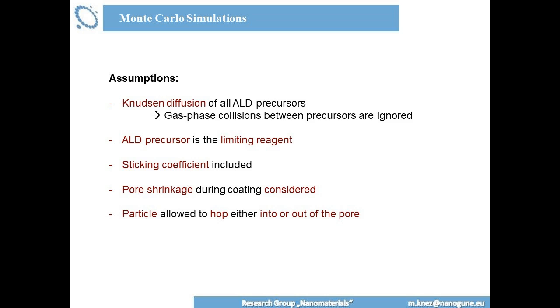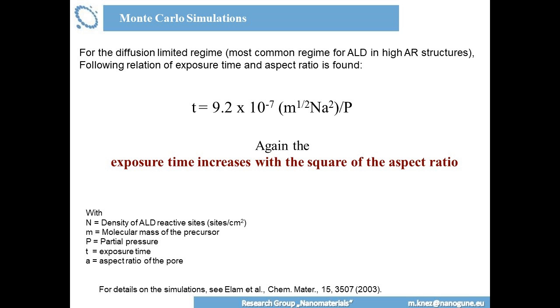So this is also considered in this model, and particles are allowed to hop in and out, so this is also a more, let's say, practical case which is considered, so not only in-diffusion but also out-diffusion. But at the end, all of this is probably going too detailed, but just to give you an idea: the Monte Carlo simulations also scaled with the square of the aspect ratio. So whatever you do, whatever you try to simulate, you will end up with something which is square or even more. The diffusion is a very, very important issue here for the precursors if you go into corrugated structures. The higher the aspect ratio, the more exposure you need.